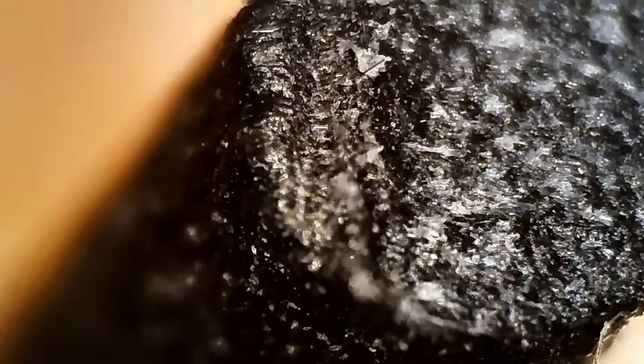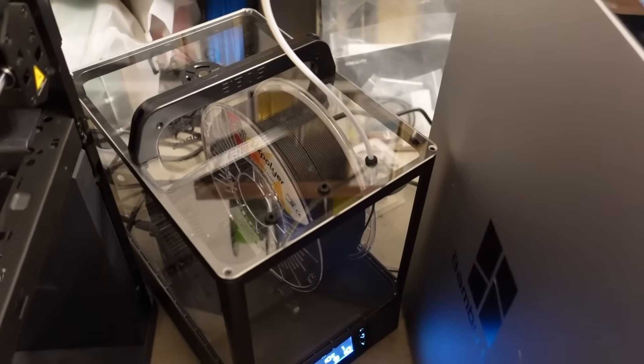This is polycarbonate under the microscope and we can see those fibers which stick out from the broken surface. With the Nylon I couldn't break it — I just cut it with pliers, and with this I just cut or bent those fibers. As already mentioned, even during printing the Nylon is in a filament dryer.